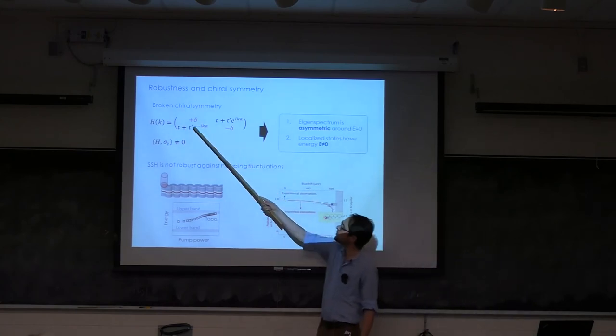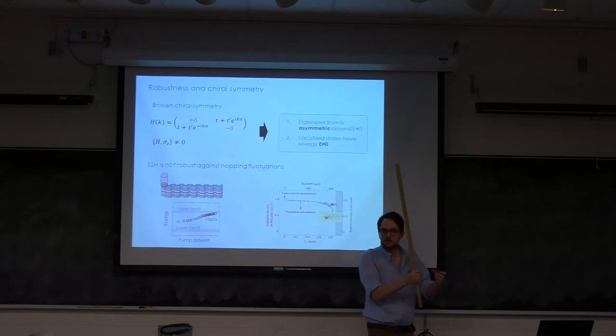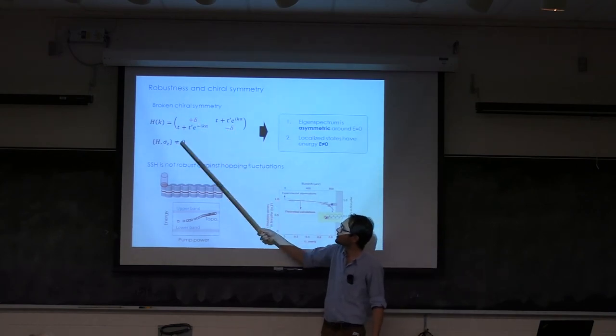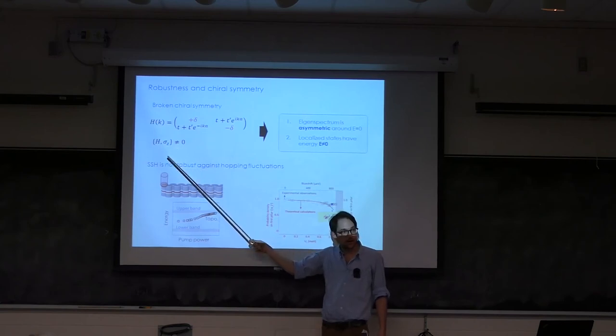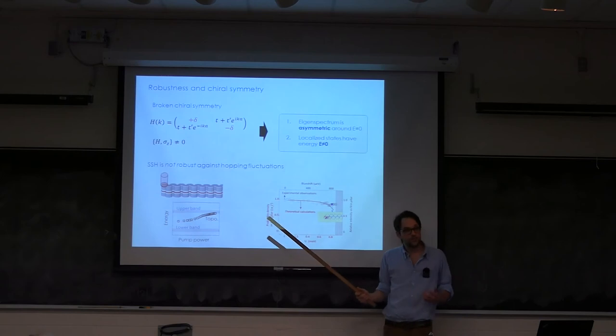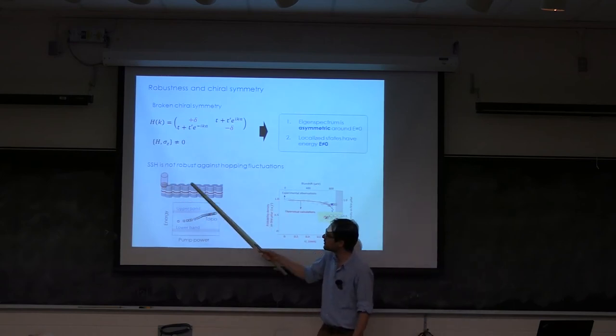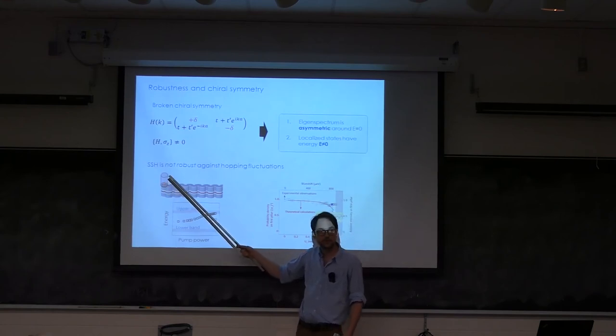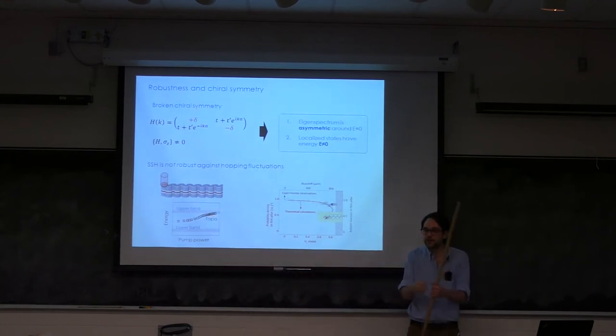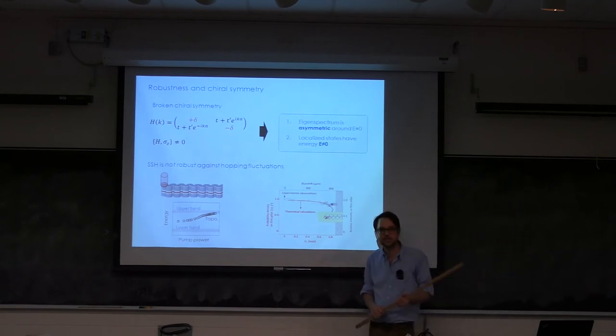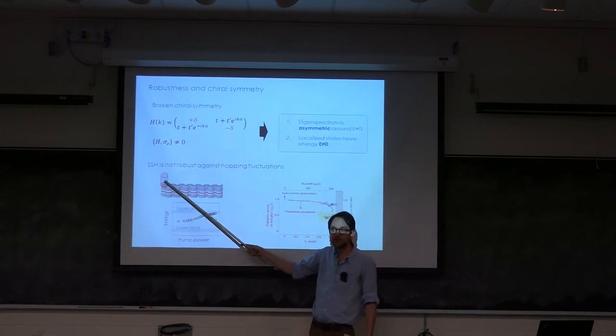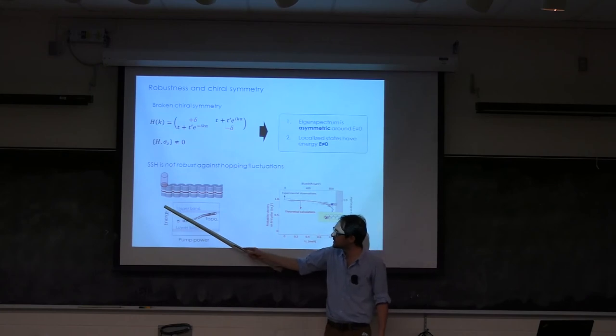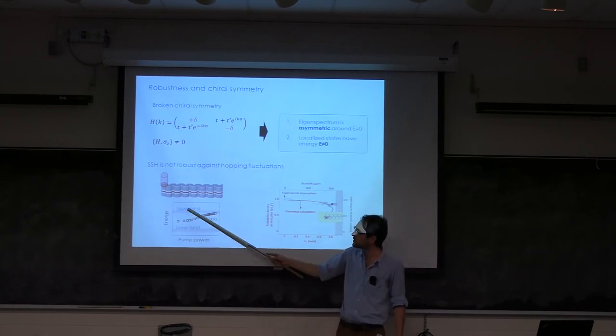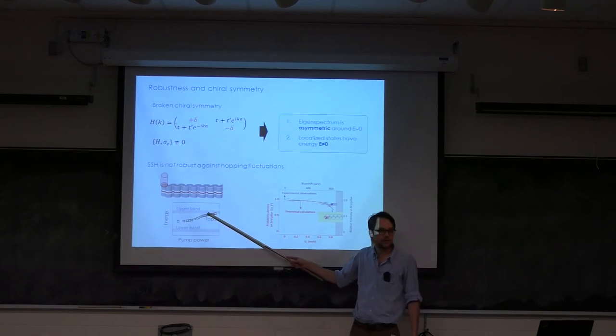However, if you have a perturbation to the on-site energy, or atoms are not identical to each other, then we have a sigma z contribution, and the Hamiltonian does not anti-commute anymore. And as a result, we're going to perturb. And so we did this experiment by doing now not an elongated spot that was illuminating the entire chain, but really localizing the first pillar. And the effect of this is that it creates a lot of electrons within this single pillar. And so because the polariton sees just a huge cloud of electrons in the environment, the effective index of refraction changes. So this is like shifting the energy of this pillar as a function of the pump power. And we see that as we do this, this is again the energy as a function of the pump power, we have our two bands that are not affected, but the topological edge state has its energy shifting continuously.